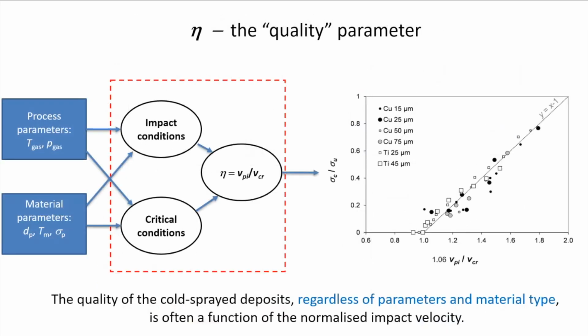Basically, what happens is that you have some process parameters and some material parameters, and these have effects on impact conditions, and also on critical conditions, which is the critical velocity. So you can squeeze all of these into this eta, and based on that, you can estimate or predict the outcome of the cold spray deposition, not only for different process parameters, but also for different particle sizes and even for different materials. That works, for instance, in this particular case for titanium and copper. With the same eta value, you end up with the same normalized strength.